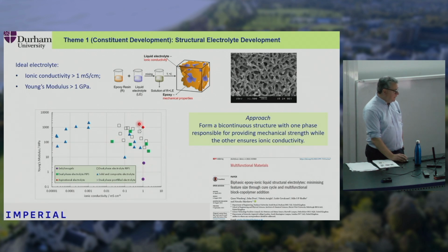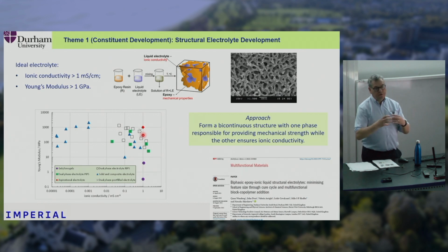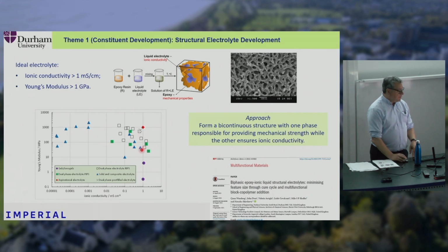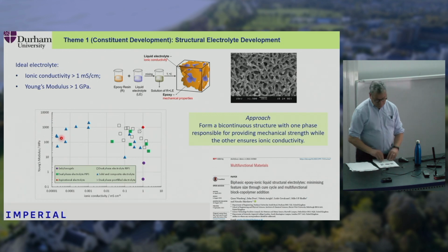So in the review that I showed you earlier, we've looked at these different strategies, and it really shows us that the dual phase electrolytes are one route, which is polymerization-induced phase segregation, or the open boxes are reaction-induced phase separation. Those are two sort of chemical routes to produce this biphasic structure. That looks the most attractive route to get a combination of ionic conductivity and Young's modulus. So that's really where we're pursuing things.